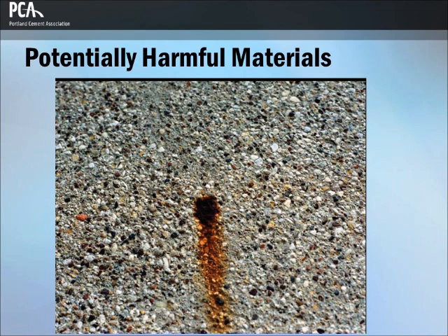As an additional aid in identifying staining particles, the aggregate can be immersed in a lime slurry. If staining particles are present, a blue-green gelatinous precipitate will form within 5 to 10 minutes. This will rapidly change to a brown color on exposure to air and light.